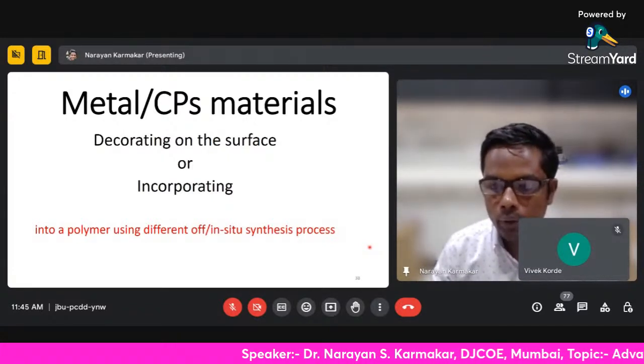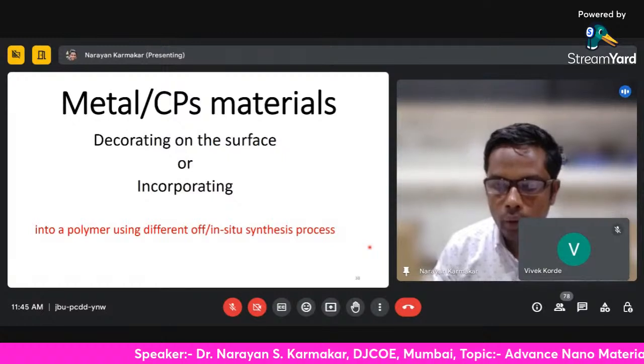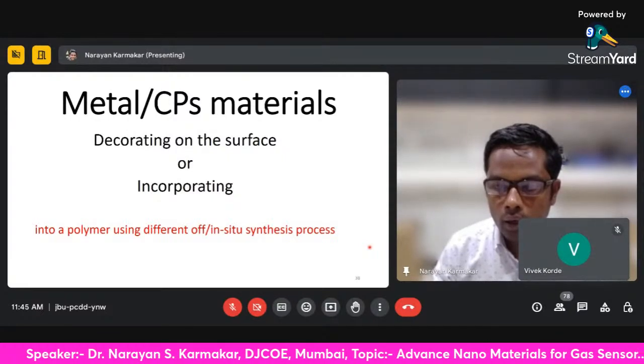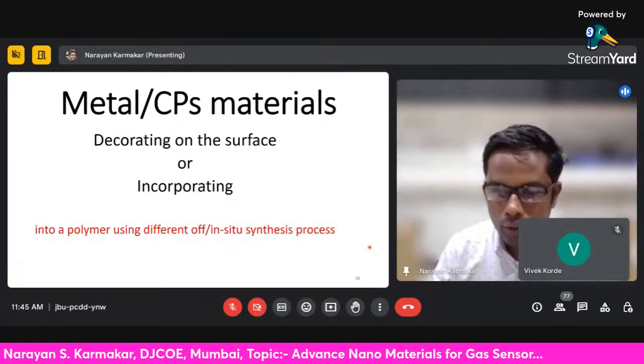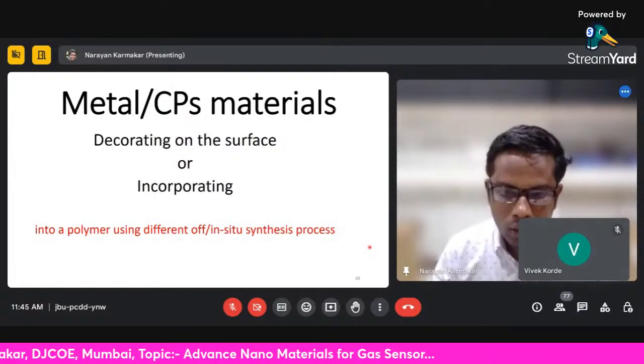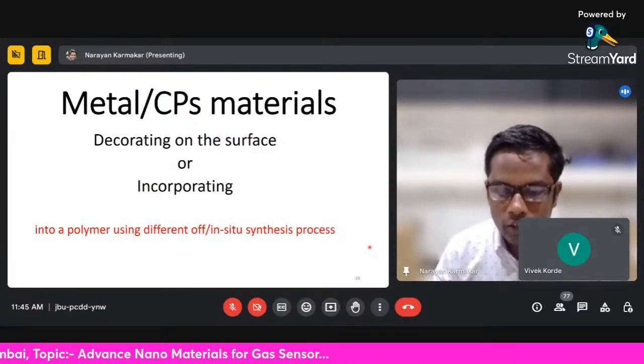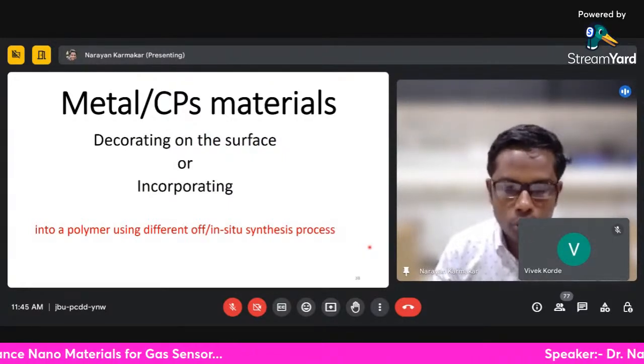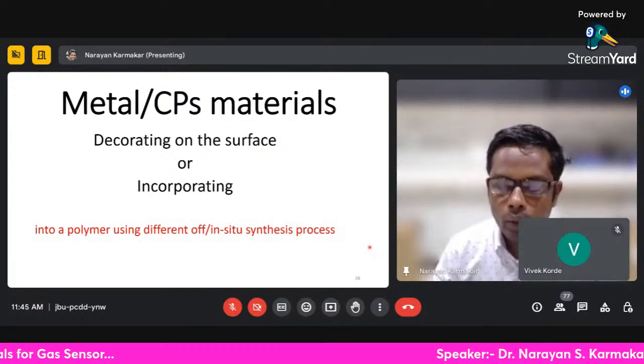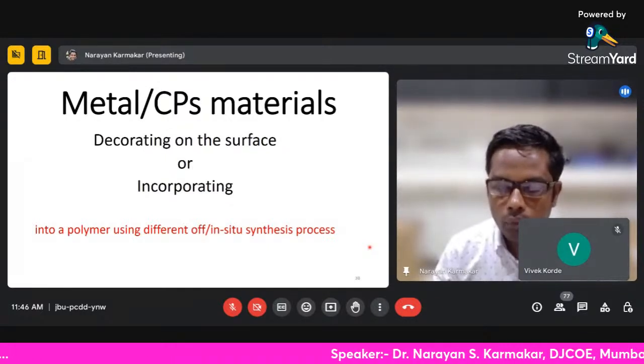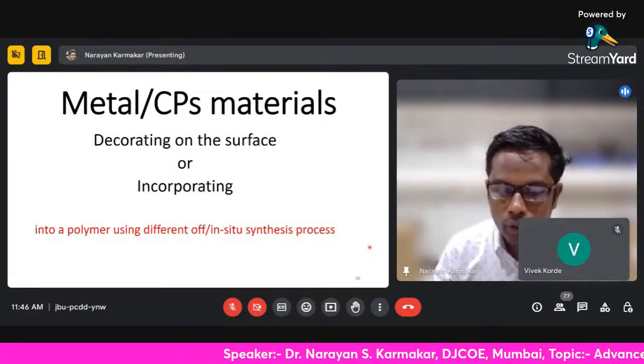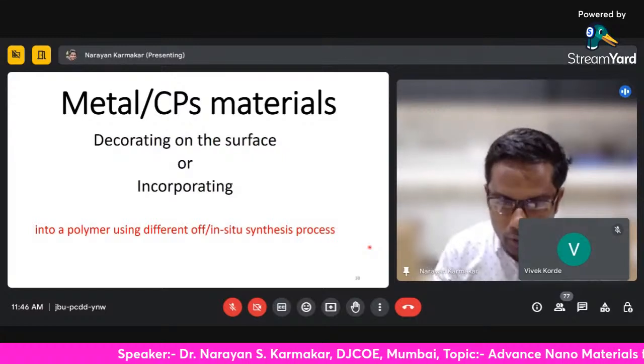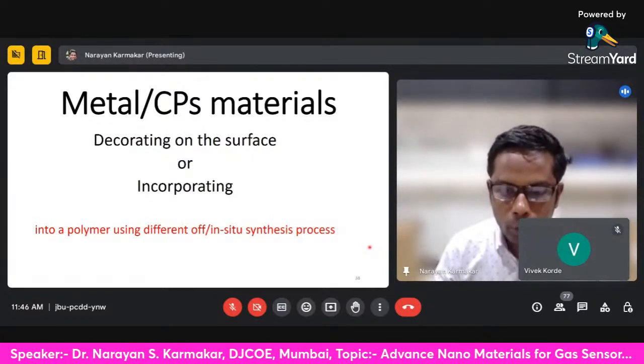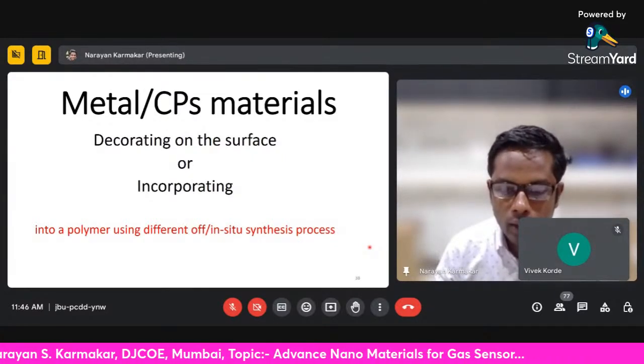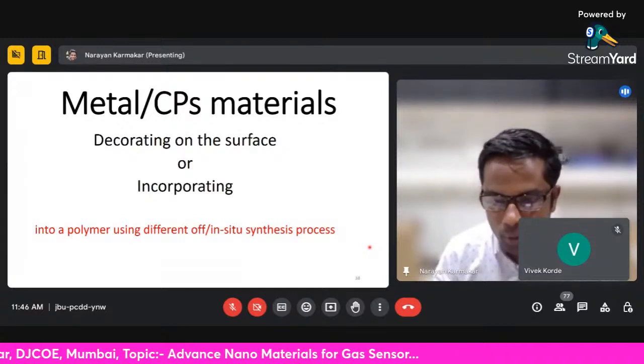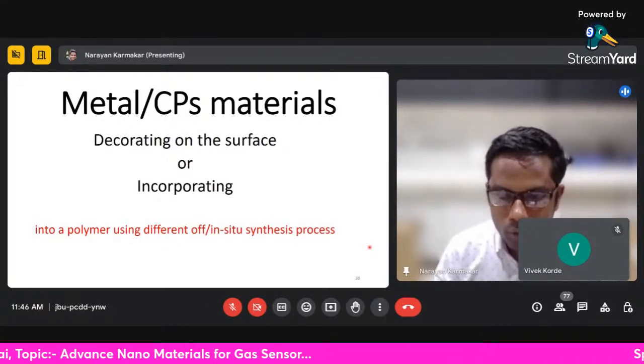It has been observed that when you decorate with metal nanoparticles, they increase the selectivity of the sensor, mainly because of electronic sensitization and the absorption of specific gases, and a particular metal changes its work function during charge distribution. So owing to these unique physical, chemical, and catalytic properties, metal nanoparticles assist in enhancing the sensing performance and stability of these gas molecules.